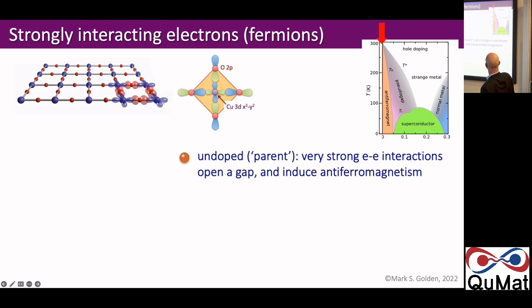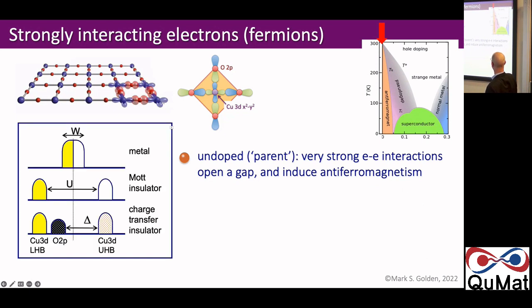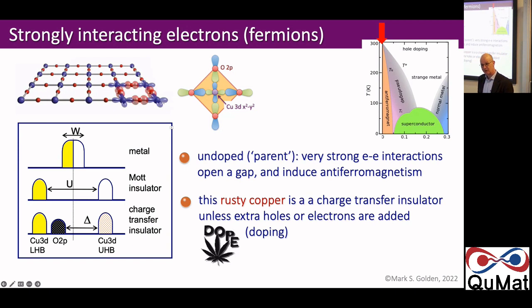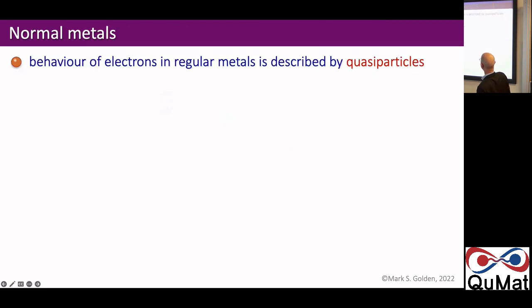Okay, so the undoped parent compound has very strong electron-electron interactions. There's a gap, and you get antiferromagnetism. Now, more people were theoreticians than not, so I don't need to show this for very long. You start with a metal, you get a Mott insulator, and oxygen 2p states in between. And it's understanding this charge transfer gap and what happens when you lightly dope this material, which is very important. So in sport, of course, you're not allowed to dope, but in chemistry and physics, we like to do this. So essentially, these superconductors are not so different from the copper inside the cables in the wall here. You just rust it a bit and put a couple of elements in there and you get something emergent and totally not understood. Maybe even very important for our management of the energy problem.